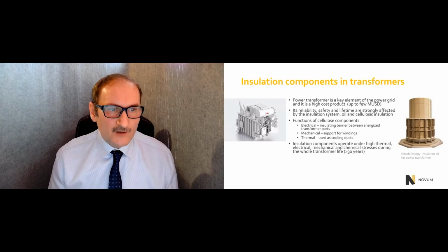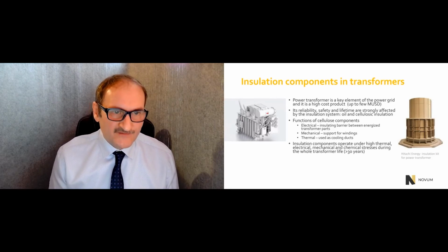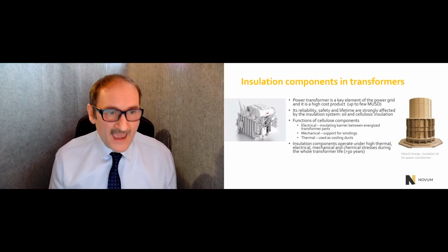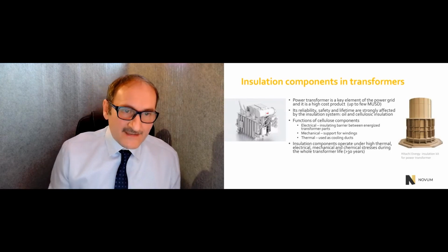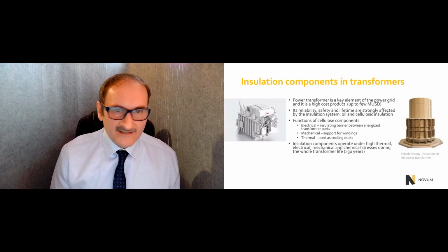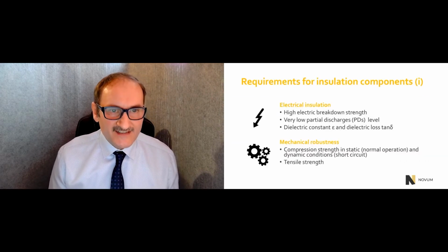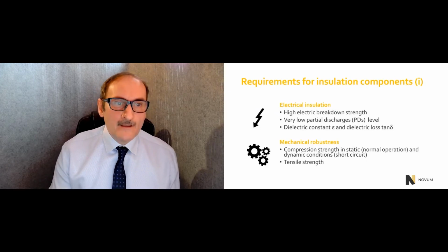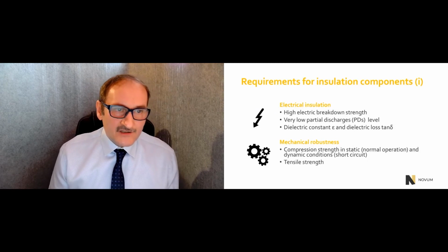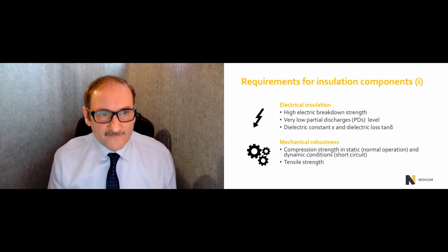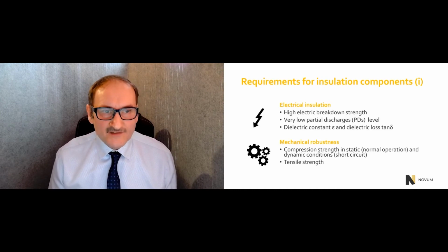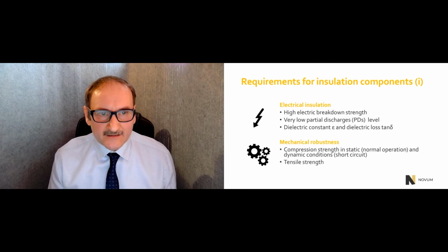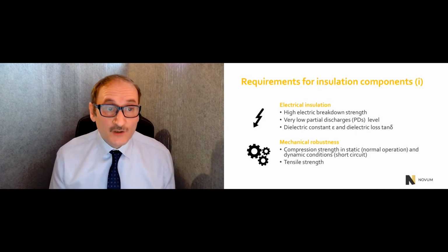Cellulose-based insulation is one of the most important components in transformer design, and it must fulfill a lot of different functions: electrical, mechanical, thermal, and also a very long lifetime. If we have problems with the insulation quality, I mean some voids or maybe some metallic inclusions, this is a disaster for the whole transformer. Electrical properties such as breakdown strength, very low partial discharge possibilities, dielectric constant, and dielectric loss, which we call tangent delta, are crucial dielectric parameters which must be fulfilled by transformer insulation.